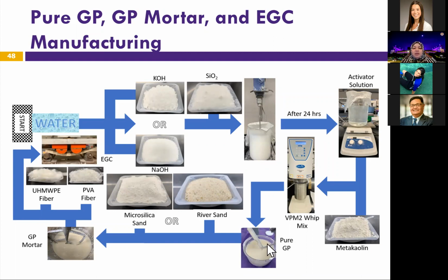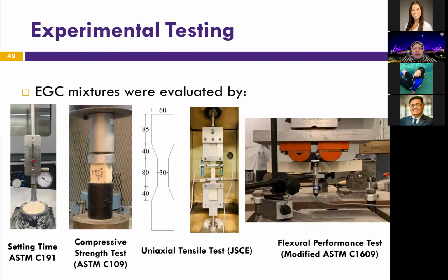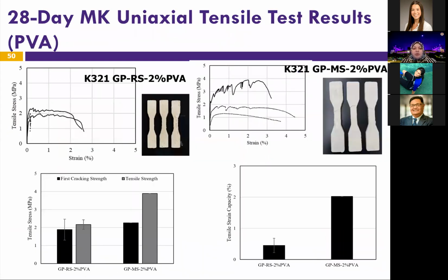until it's completely homogeneous. That takes some time, between 15 and 30 minutes. That gives you the pure geopolymer. And then after that, you add the sand, whether it's river sand or microsilica sand. And then we add the fibers, whether PVA fibers or polyethylene fibers. And that's when you get the geopolymer mortar that we put in the molds. And when it cures, it becomes engineered geopolymer composites. We did a whole spectrum of testing: setting time, compressive strengths, uniaxial tensile test, flexural strengths. And now I'm going to show you some of the results.